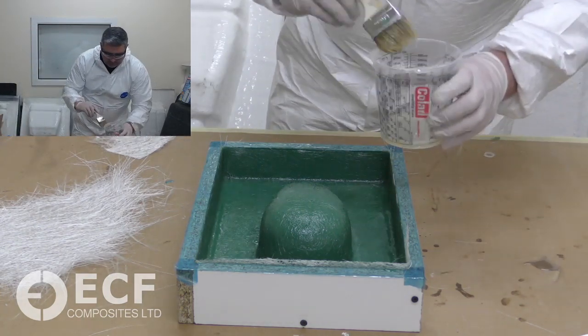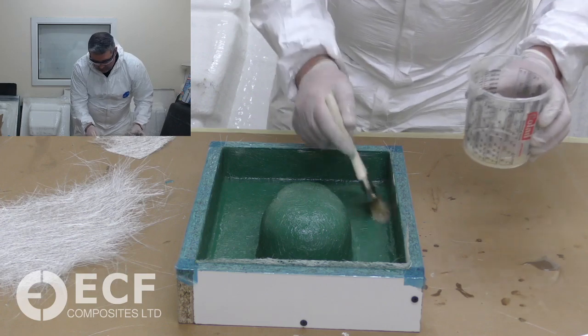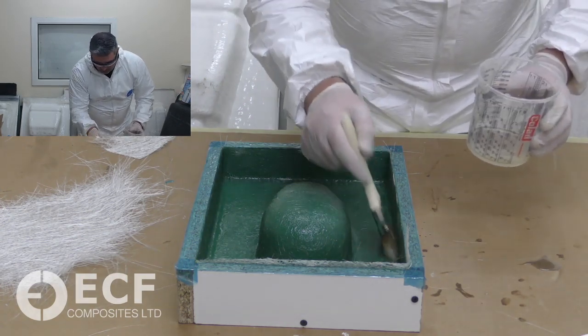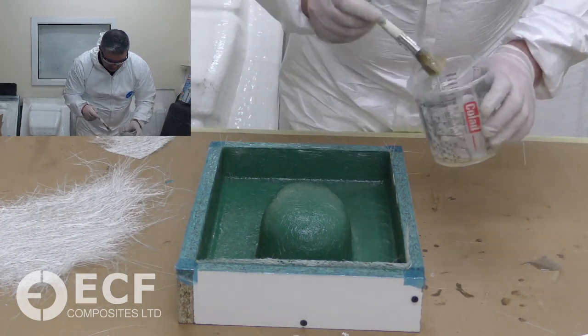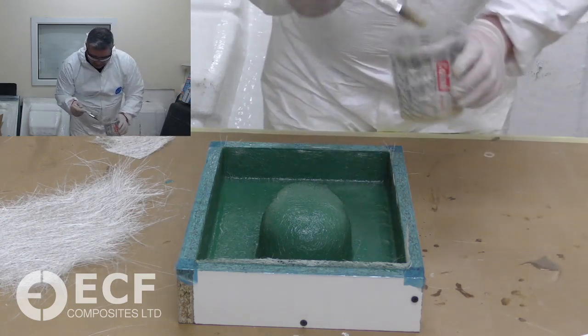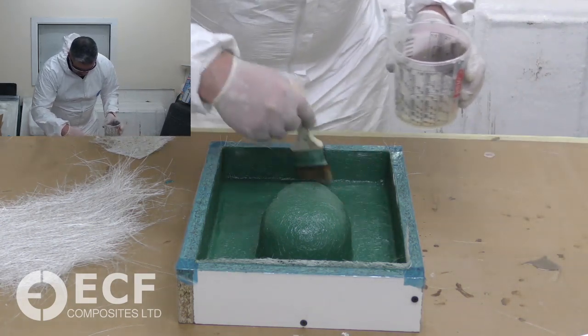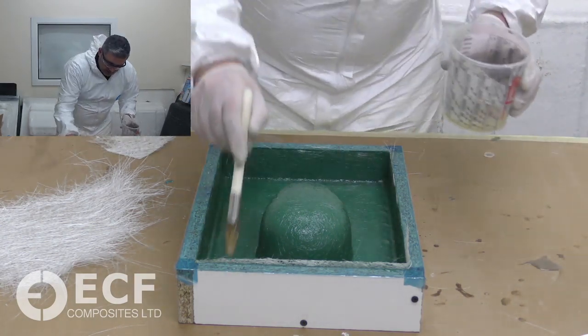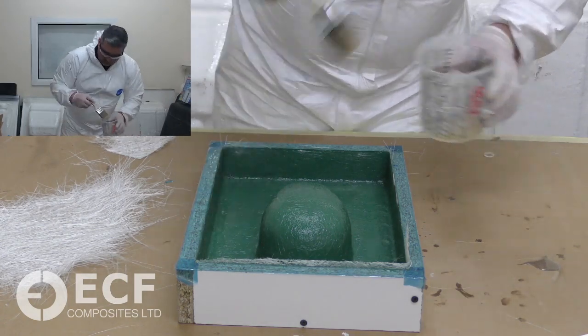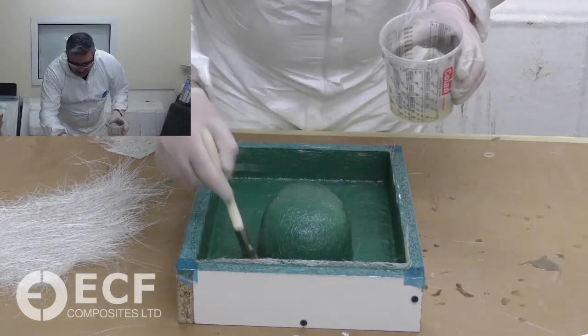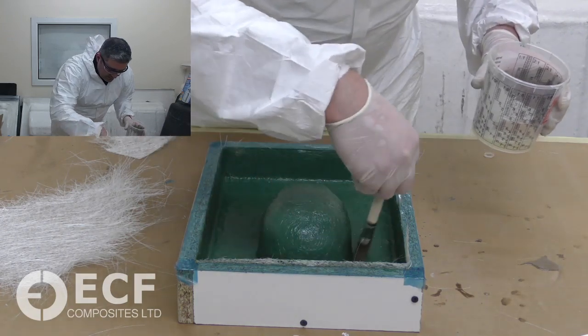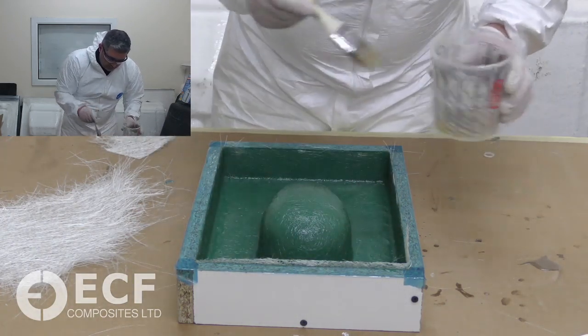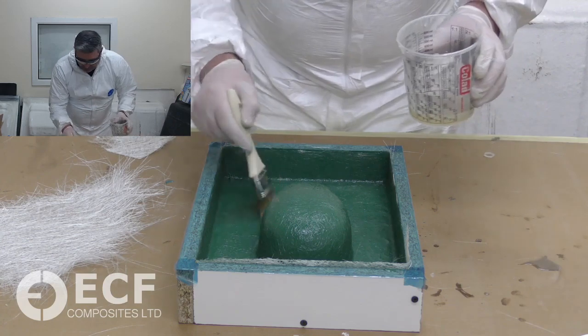And then get rid of any excess resin. Just go around those corners again with a brush, just to flatten down any disturbed fibres. You see, I'm just mopping up any excess resin as I go. The reason I'm doing that is I don't want any areas to be resin rich, because that will cause weak areas on the surface of the mould.